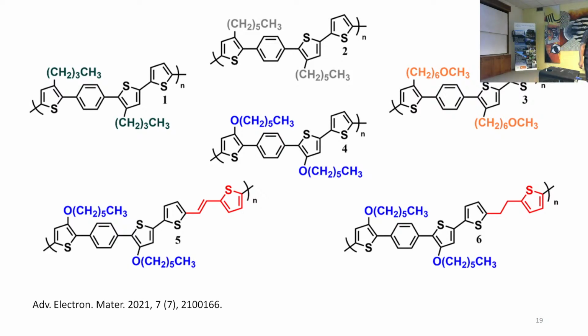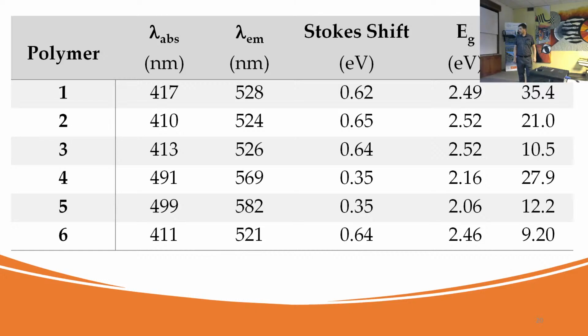We did it anyway. Why did we do this polymer anyway? Because red color and blue color exist and are easy to make in electrochromic devices. But there is one color that is particularly difficult to do, which is the yellow. And so we try to achieve the yellow by breaking the conjugation in here, hoping that it still works as an electrochromic device. Here are some numbers, okay? Briefly, the fluorescence quantum yields in chloroform are always high. In one case, it reaches 35%, which is quite good. If you put it in a more rigid media, surely it will go above.